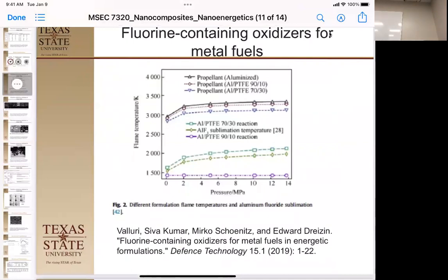is low. So on this one right here, what they were doing is trying to use fluorine containing oxidizers. Now, do you want to use fluorine gas as an oxidizer? No, it's horrible to deal with, right? So what they're doing is using Teflon and Viton, which are fluorinated polymers, as your fluorine source. And then the metal fluoride bond should be stronger than the carbon fluoride bond, and therefore it's going to produce carbon black and your fluorinated materials here.